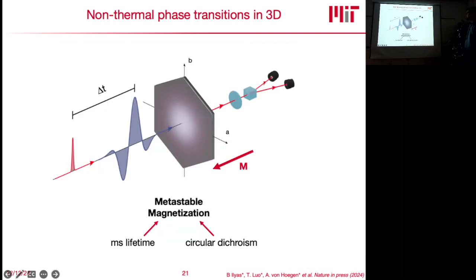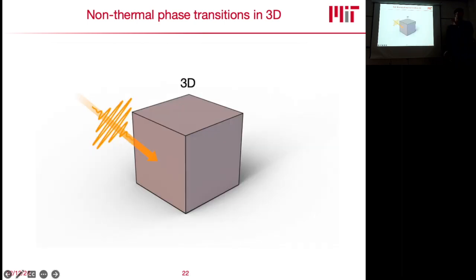And so this then basically brings us to a summary of the results of this experiment, where we use terahertz excitation on this antiferromagnetic insulator, and we create a metastable magnetization. All of what I've shown so far is doing these experiments on 3D materials. This was still a bulk material, still macroscopically thick, like micrometers. So it's very far away from the two-dimensional limit.